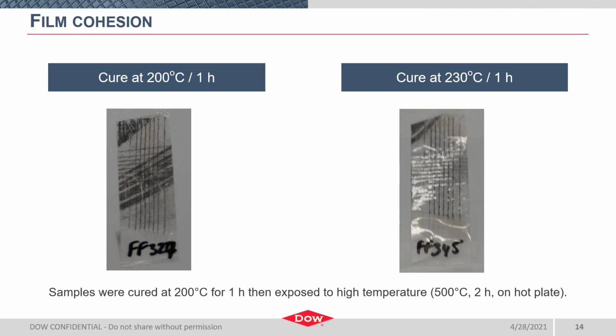This performance property evaluated for 2 coating samples cured at 200 C, shown on the left, and then 230 C, shown on the right. And while 200 C is sufficient to cure the film for many performance properties that I've outlined already, the film cohesion was improved slightly when the curing temperature was increased to 230 C. And this again is just going to give us some flexibility in formulating an application depending on the desired performance.